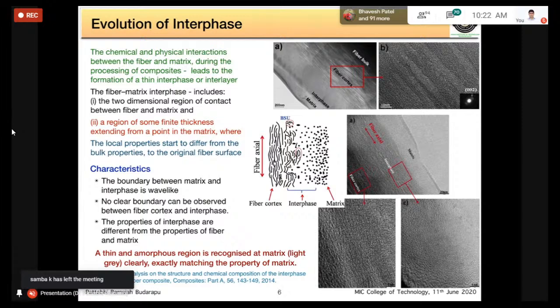This small region decides the behavior of the fiber matrix composites. So the bottom line is a thin and amorphous region is recognized at the matrix, that is light gray, clearly matching the property of the matrix. Exactly towards the end of the interface, the properties are matching with the properties of the matrix. But at these scales, you can see the wave-like structure, and there is no uniform shape or size for the interface.